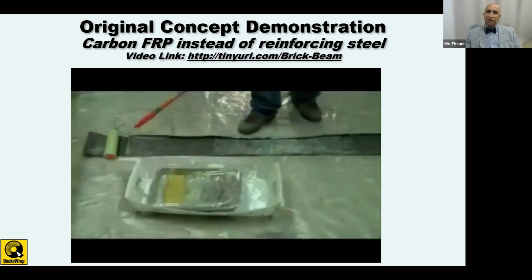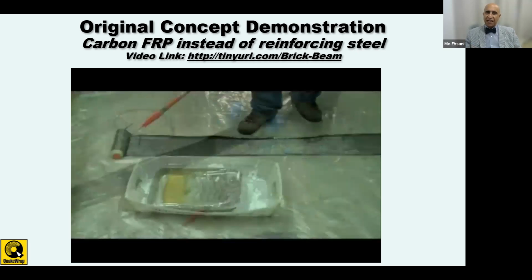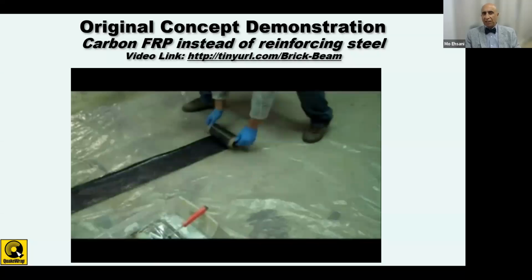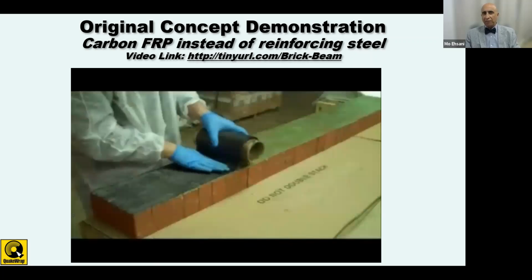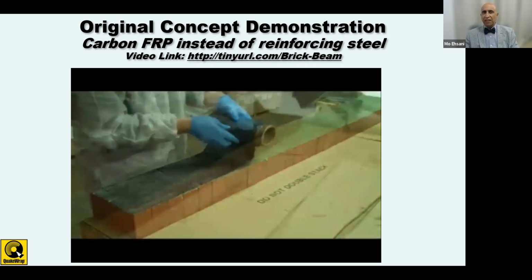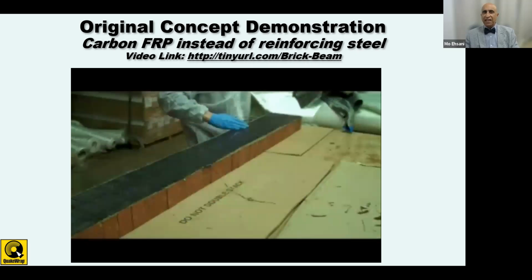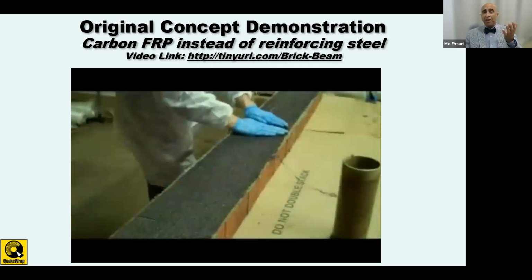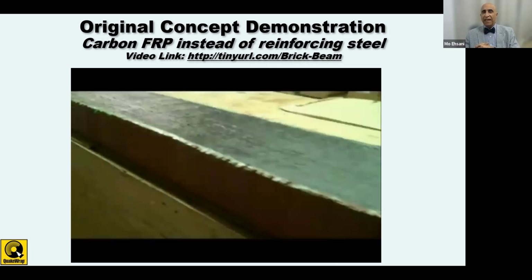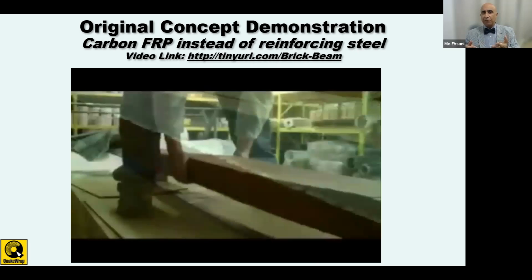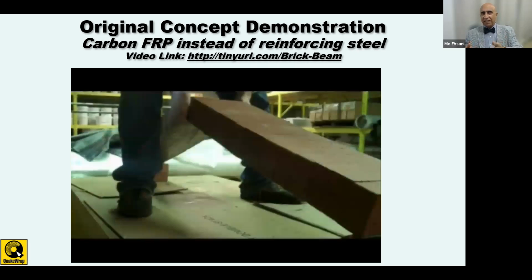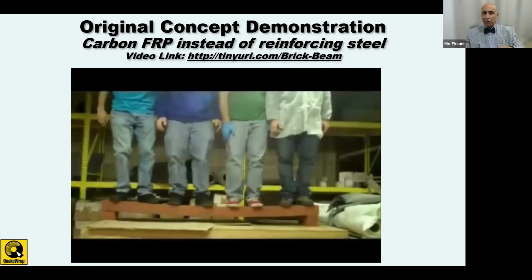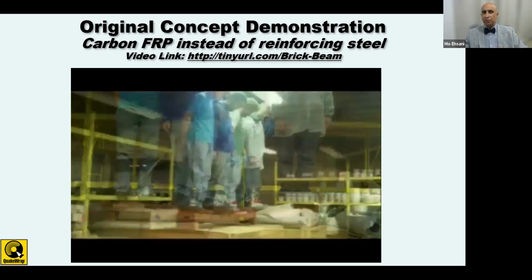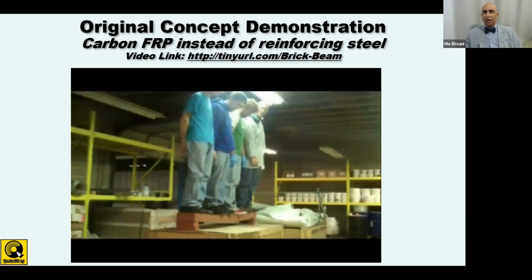We roll that into the fabric, and once it's saturated, you pick it up, put it on the back of that brick beam, and work it out with your hands to get rid of any of the air bubbles. This takes maybe about half an hour or so to make. You let it cure in ambient temperature until the next day. In this direction, the bricks don't have any strength, but when you put the fabric in tension, it can support the weight of those 4 guys standing on it.